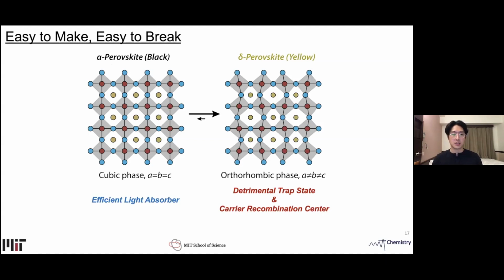Now, unfortunately, at room temperature, the thermodynamically preferred state is the delta phase, which means a perovskite stabilized to an alpha phase can readily convert to delta phase when exposed to destabilizing environments. So this justifies developing a delicate surface passivation strategy.